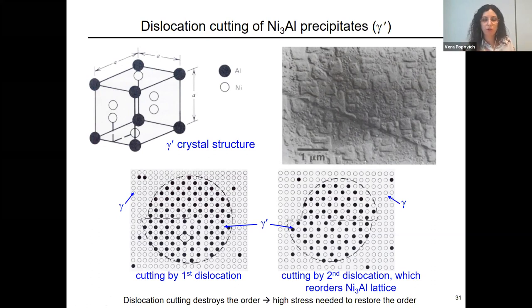So high stress is needed to restore the order. And this is one of the reasons why it's difficult to cut through such gamma primes. When we talk about nickel-based superalloys, up to 900 degrees you want to have gamma prime precipitates because they are the ones that strengthen the matrix. But above approximately 900, 950, these gamma primes tend to coarsen and dissolve. So in the next few slides, I show you what is done to tackle that if the temperatures need to go higher. What kind of approaches can be used there?